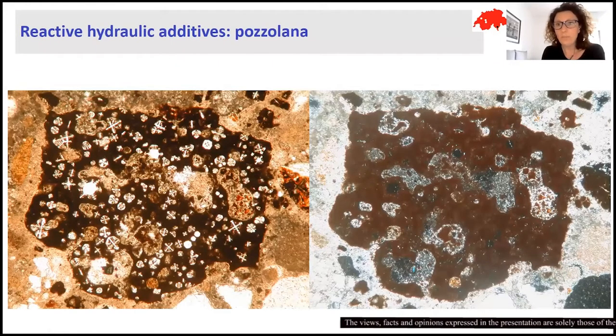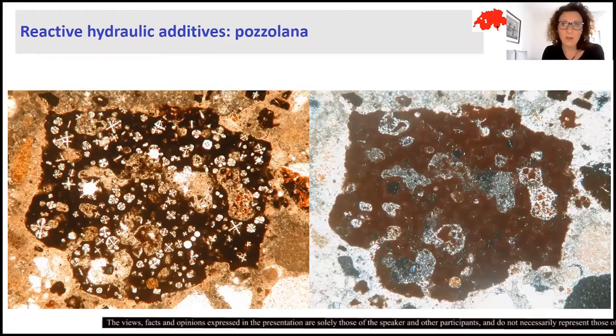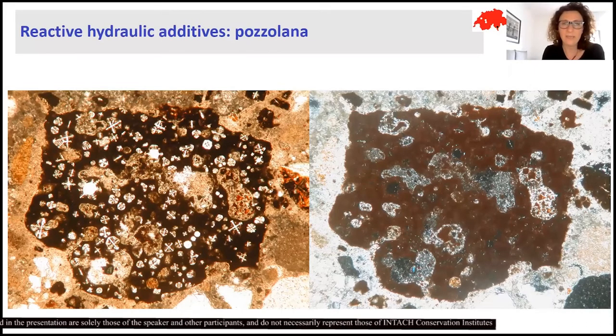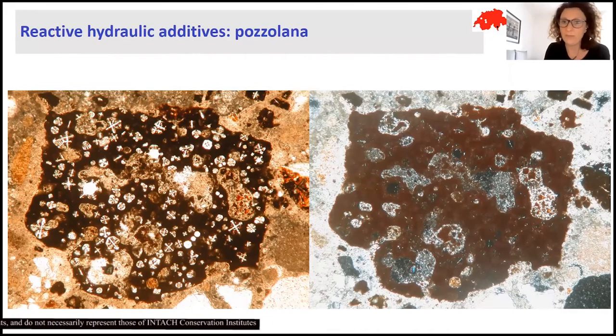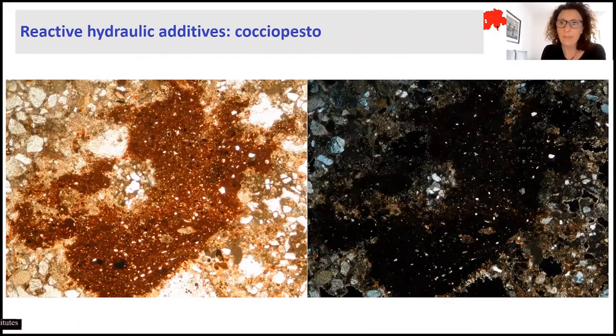The other possibility to obtain a hydraulic mortar is the addition of reactive aggregates, such as, for example, pozzolan or cocciopesto material, and these are materials I can easily characterize, because they are also easily distinguishable by the microscope. It is very important to see that these materials have reacted with the binder. Normally this material should be dissolved within the binder, and I should see the reaction edge between the aggregate and the binder.